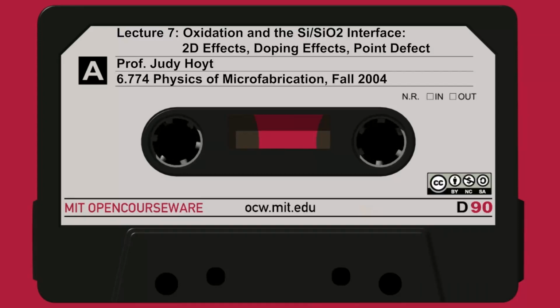Okay, so the diffusion rate through the oxide and the surface reaction rate are now all going down as a function of stress. And where is there stress? Well, there's a lot of stress in this corner region, because the oxide has to push up against this nitride film. So what you see here is, look at the amount of oxide that was grown in this bird's beak area. Quite a bit has grown, the thickness here. Compared to the bird's beak area, when you turn the stress model on, not so much oxide has grown.